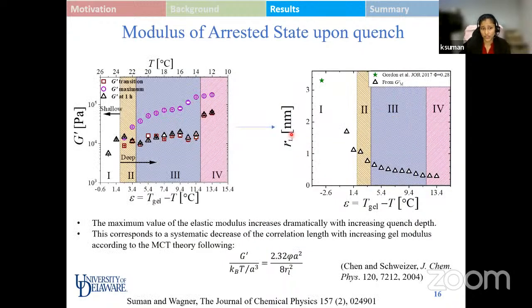With the knowledge of G prime in the aging experiment, we can relate it using the naive mode coupling theory as proposed by Chen and Schweizer, and it can be related to the localization length. Using the values already computed experimentally, we now estimate the value of localization length and plot it as a function of depth of quench.